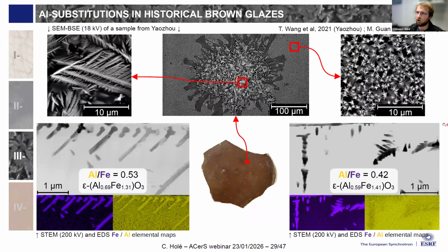And what's very important, of course, is to compare these results with ancient ceramics. And we found out in samples from Yaozhou that indeed we have, in big and in small dendrites, a lot of aluminum, at more or less the same rates that we found in the mock-up samples. And we can even note that the bigger dendrites have slightly more aluminum than the smaller dendrites, which we observed once again in the mock-up.